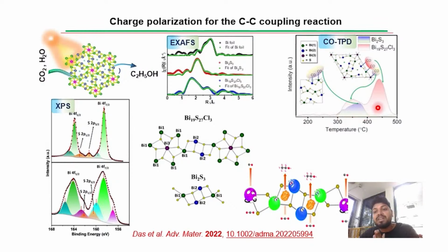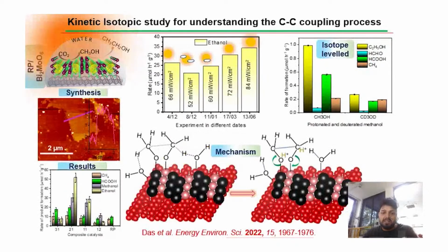One CO desorption is at higher temperature. That means some bismuth centers are adsorbing the CO in a stronger way, and these CO are coupling with each other and giving the multi-carbon product, which is ethanol over here. On the other hand, the other bismuth site, which is bismuth 3 over here, is staying as it is and performing CO2 to CO production. However, for Bi2S3, we got only CO as a product. Therefore, because of the different polarization in these 2 bismuth centers, we got ethanol as a major product.